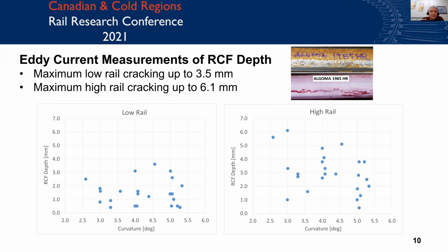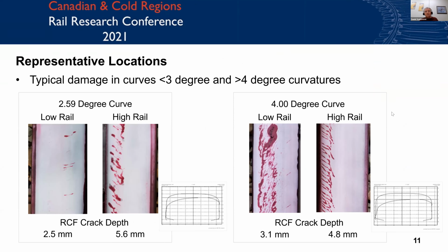So that analysis led us to select those curves and then go out and measure the curves that we thought might be the problem, and then find out that they actually do have those types of cracks that we saw in the rail that led to the derailment. We thought this was the A to B to C to D. That analysis led us to the solution of identifying those locations that had those types of cracks. So visually, what we saw in track, essentially for a 2.6 degree curve, was a lot of plastic metal flow in the high rail.